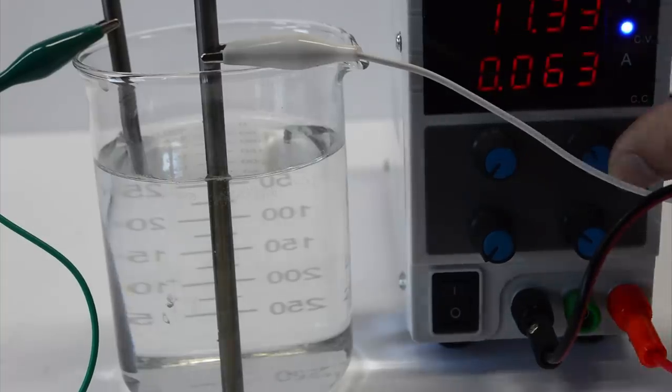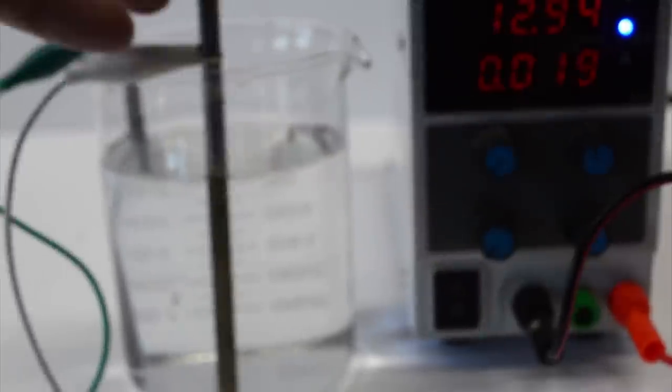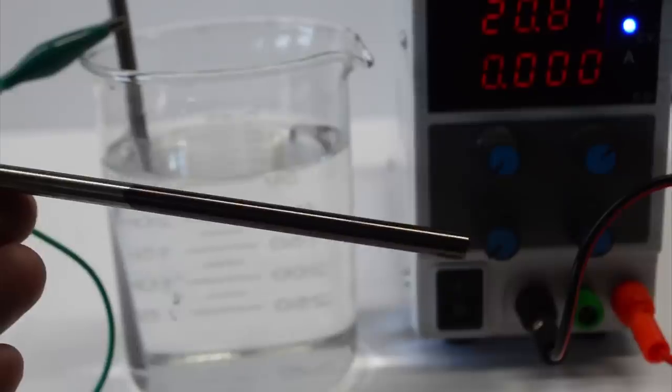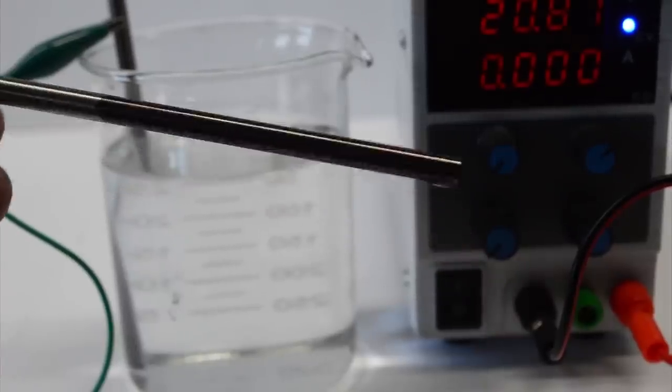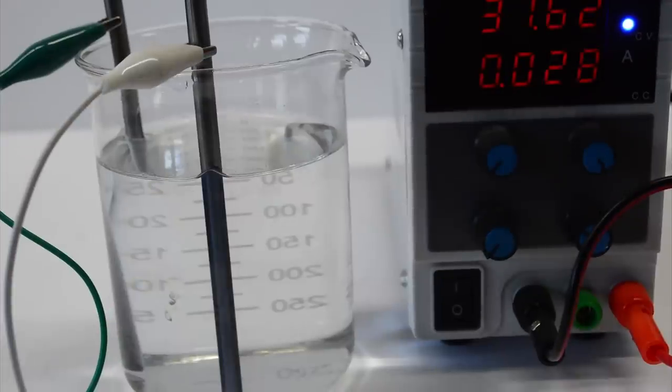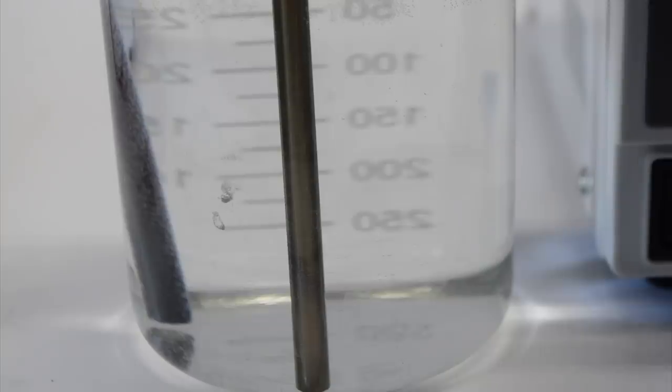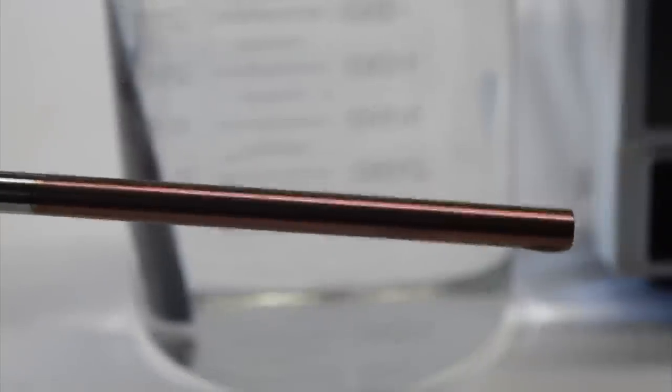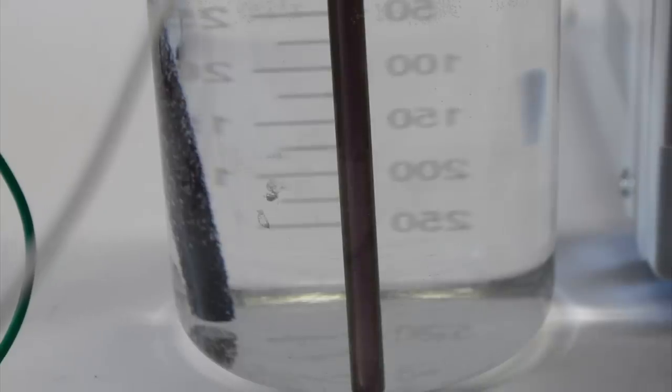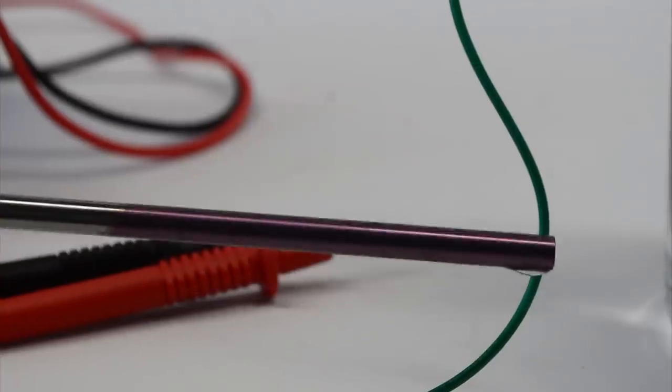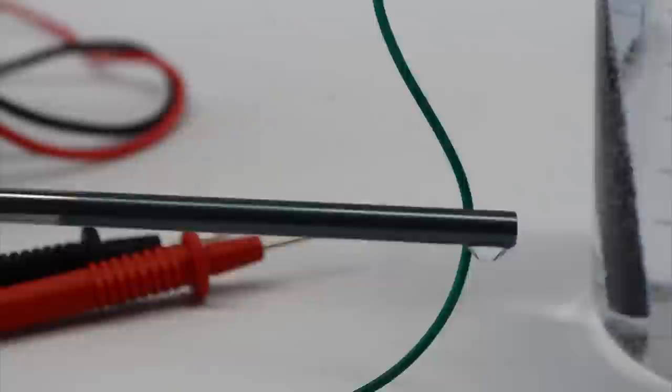As with the flame method, it starts yellow at around 5 to 15 volts, slowly getting more bronze until you get purple at around 25 volts. By about 30, my power supply maxed out, but it's more than sufficient to get a beautiful blue color. To get the higher voltages, I'm using the DC to DC voltage converter from my gel electrophoresis setup. It can't do low voltages, so it skips pretty quickly to the second yellow. As I continue to crank the voltage, we eventually get this phenomenal red color. And then as we pass 100 volts, we eventually get a really gorgeous purple, and then finally a dark green.